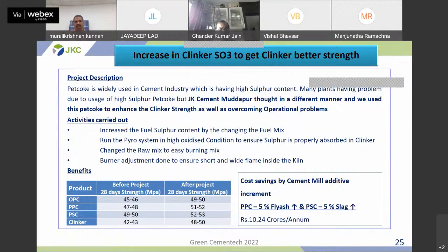For that, we have carried out several activities such as increasing our fuel sulfur content by changing fuel mix, changing our raw mix to an easy burning mix, and running our pyro system in highly oxidized condition in order to ensure sulfur is absorbed in clinker, and doing some burner adjustment to get a short and wide flame.